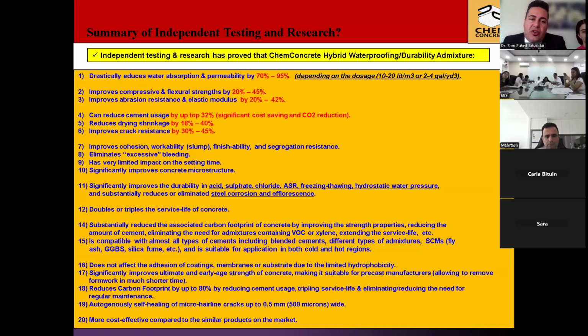It improves compressive and flexural strength by 20 to 45%, improves abrasion resistance and elastic modulus by 20 to 42%. It can reduce cement usage by up to 32%, usually 16 to 32%, which provides cost saving and also CO2 reduction. It can reduce drying shrinkage by 18 to 40%, improves crack resistance by 30 to 45%, and improves cohesion, workability, slump, finishability, and segregation resistance.